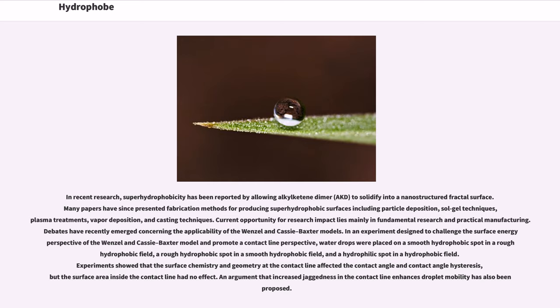Debates have recently emerged concerning the applicability of the Wenzel and Cassie-Baxter models. In an experiment designed to challenge the surface energy perspective of the Wenzel and Cassie-Baxter model and promote a contact line perspective, water drops were placed on a smooth hydrophobic spot in a rough hydrophobic field, a rough hydrophobic spot in a smooth hydrophobic field, and a hydrophilic spot in a hydrophobic field.